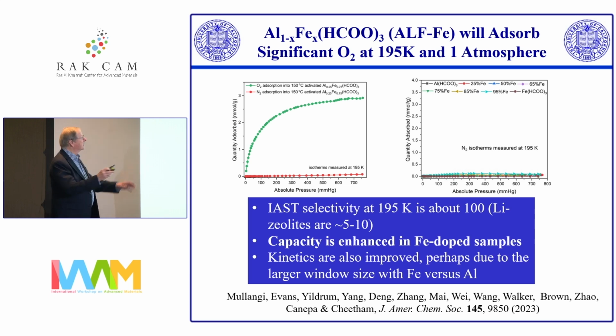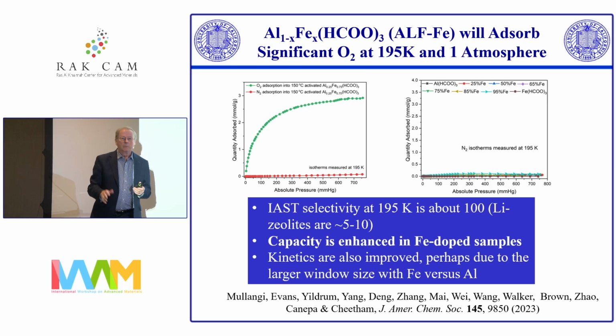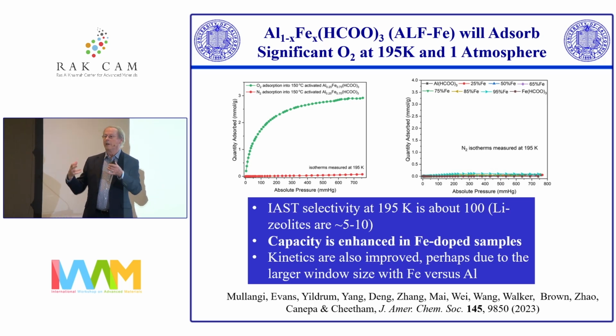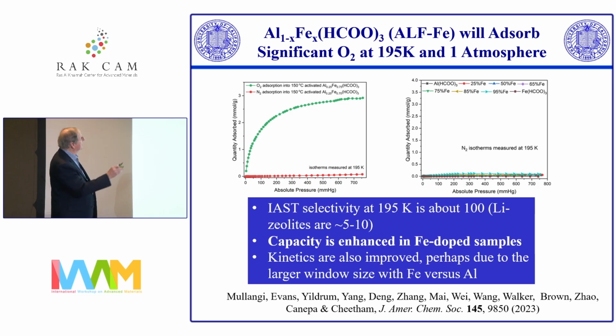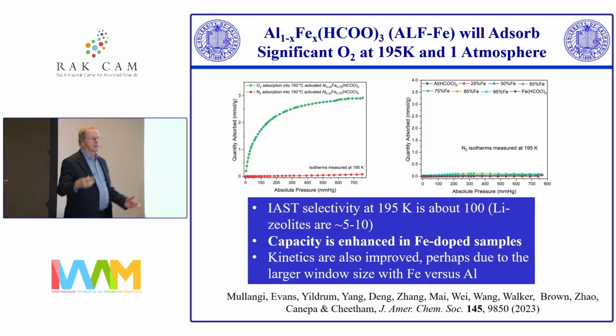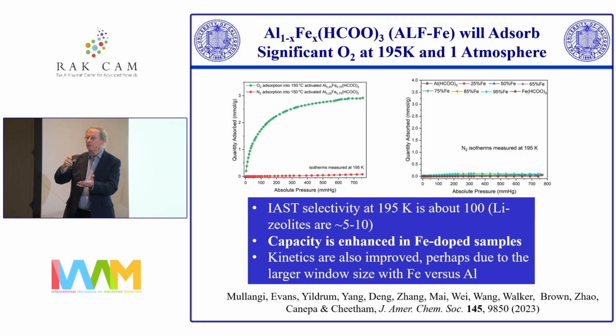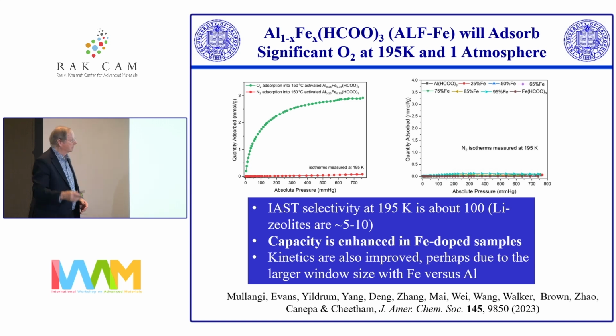So let's see what happens with O2. The good news is that ALF will absorb O2. This is data for the iron-doped system. This is the nitrogen again here. So we have a selectivity of about 100 for oxygen over nitrogen. Just notice, this is the other way around. It's not like the zeolite. We're absorbing the oxygen that we want instead of absorbing the nitrogen that we don't want, which is 80% of the air. So this has a massive advantage over the zeolites. We're absorbing the stuff that we need. And the downside, when we initially did this and published it, is that we need to cool it down to about 200 degrees Kelvin, to dry ice temperatures, in order to make it work, because the heat of absorption of oxygen is not as good as the heat of absorption of CO2, which we can easily do even above room temperature.